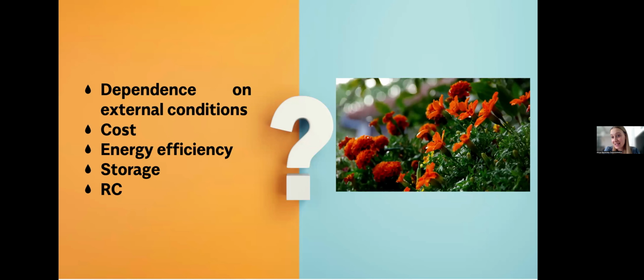Despite the advantages of this technique that I presented to you, obviously there are some limitations and there are some issues that we have to think about. I would like to start with the dependence on external conditions, as this process can be sensitive to external environmental conditions because we are using air dehumidification. As we are working with air dehumidifiers, they have their limitations as the equipment. And if we really intend to lower the drying air humidity below 1 gram per cubic meter, or even to 0, if we know that the weather was not really favorable that day and it was raining and the air humidity of external air was quite high, it wouldn't be possible to lower the air humidity to that really low level. That is why over here that is quite a limitation, dependence on external conditions.